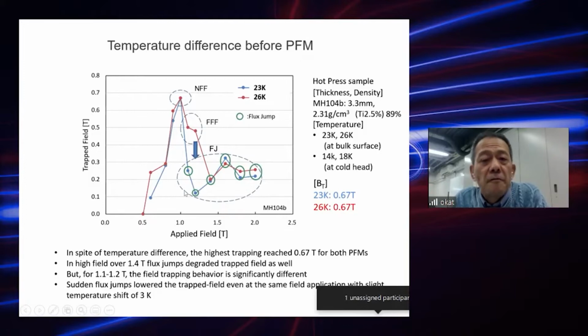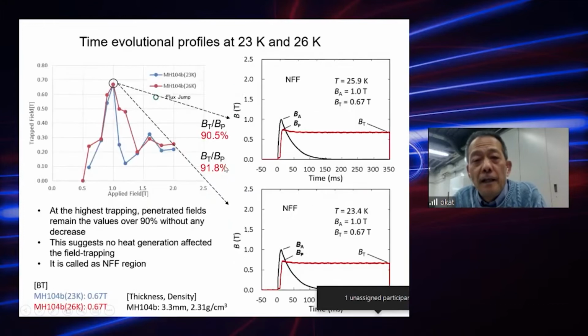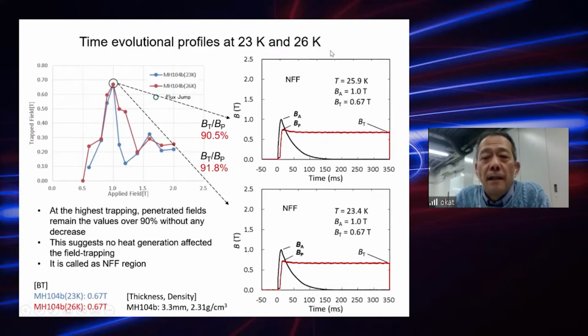But for the region 1.2 and 1.1, in this region, shown in the blue arrow, the field trapping behavior is significantly different. So sudden flux jumps lowered the trapped field, even at the same field application with slight temperature difference of 3 Kelvin. So then we want to say the reproducibility of the PFM is a little bit astonishing.